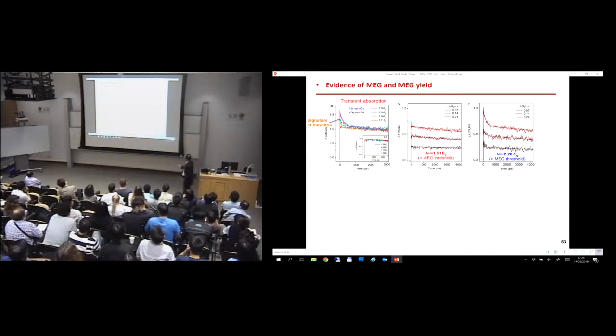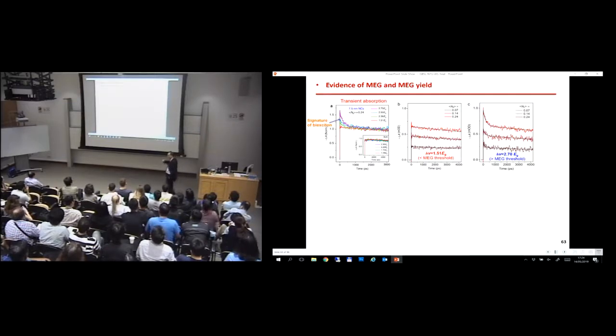Now, we make use of transient absorption to look for evidence of the MEG, multiple exciton generation. In fact, we were looking at the signature of the bi-exciton. Experiments have to be done very carefully to make sure that your excitation fluence is very low. Otherwise, if you have a high excitation fluence, you can still create a multiple exciton, but that's not the MEG phenomenon that we are trying to chase. What we want is to perform the experiment at very low pump fluence, and we perform the excitation below the MEG threshold and above the MEG threshold.